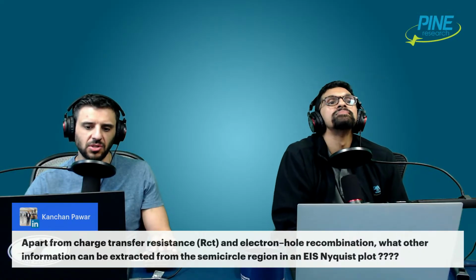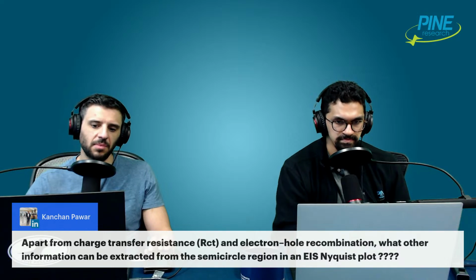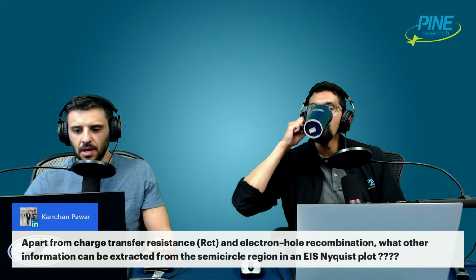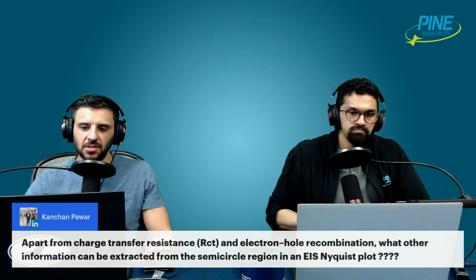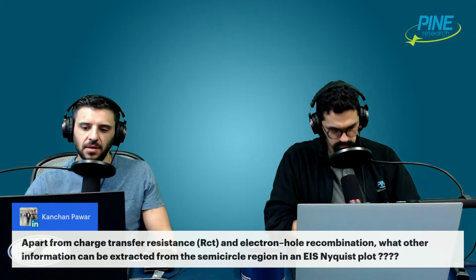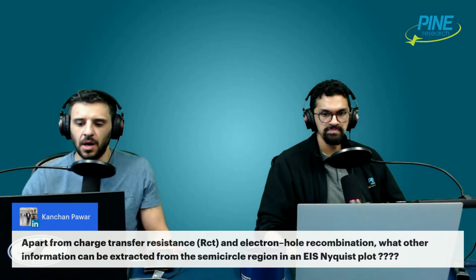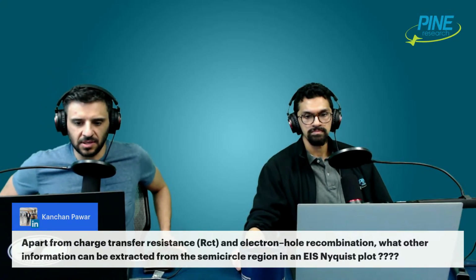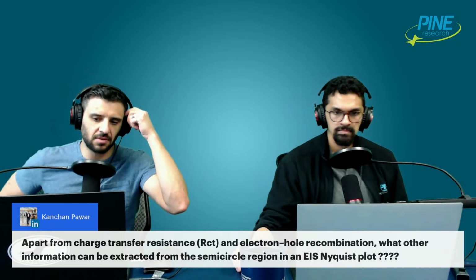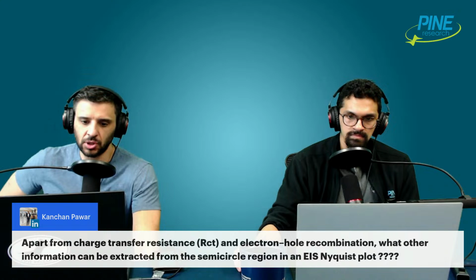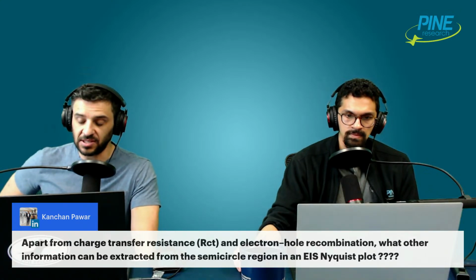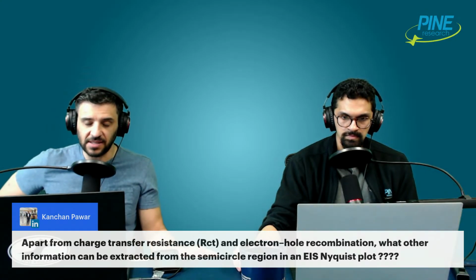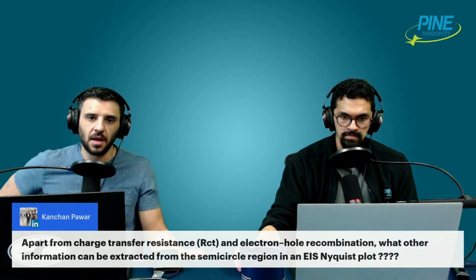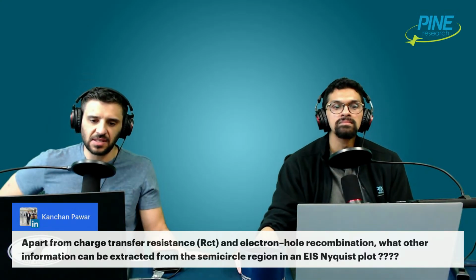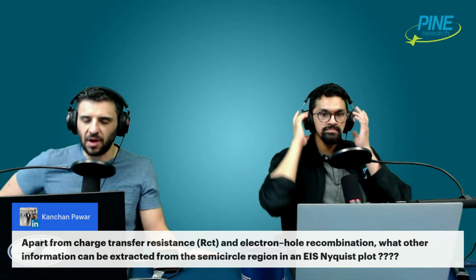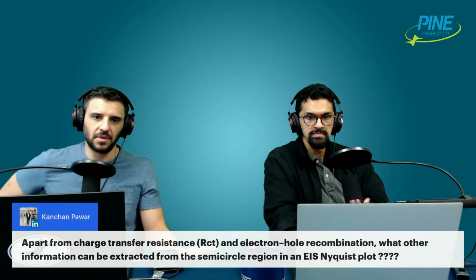But Kanchan had asked, apart from charge transfer resistance, RCT, and electron-hole recombination, what other information can be extracted from the semicircle region in an EIS Nyquist plot? One of the main things is a time constant, actually. There is a way mathematically to get the capacitance value from a Nyquist plot, but more often, for the semicircle region in a Nyquist plot, you do a circuit fit and you get the R and the C values, right? The charge transfer resistance, which is the width of that semicircle, is associated with a charge transfer process, and that process has a certain speed associated with it, which is related to its kinetics. And the multiplication of R times C is called a time constant, tau. It is, roughly speaking, the amount of time for 60% of the capacitor to be charged up.